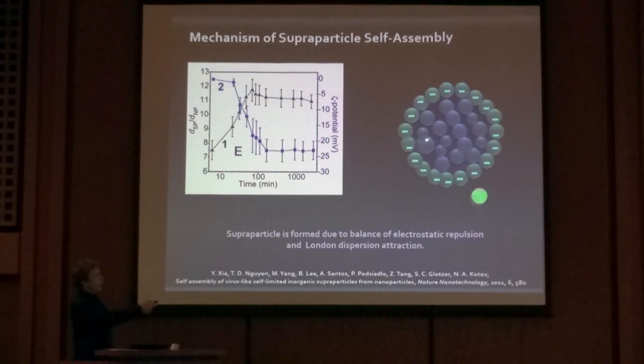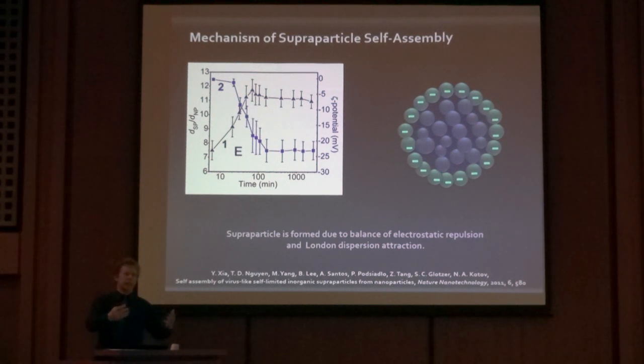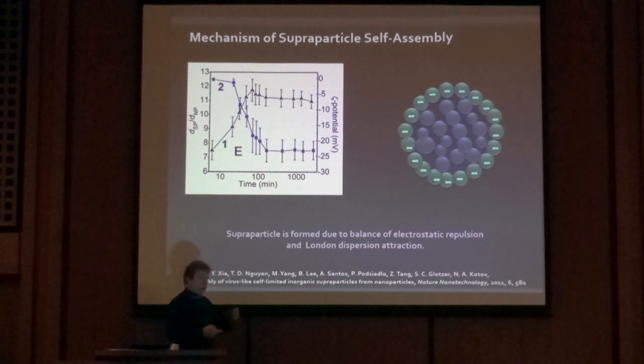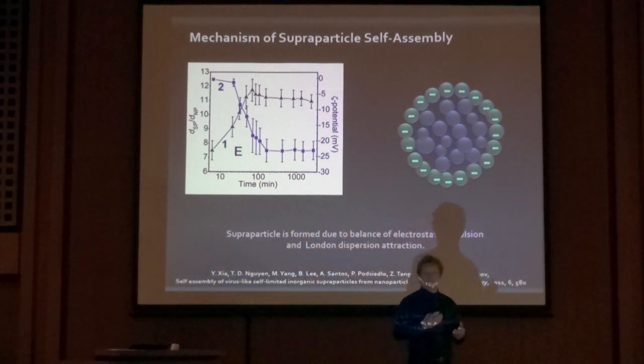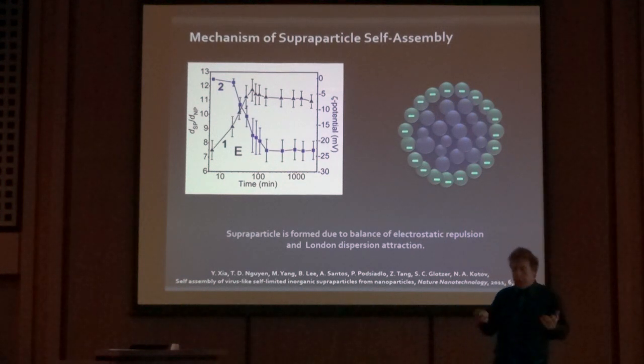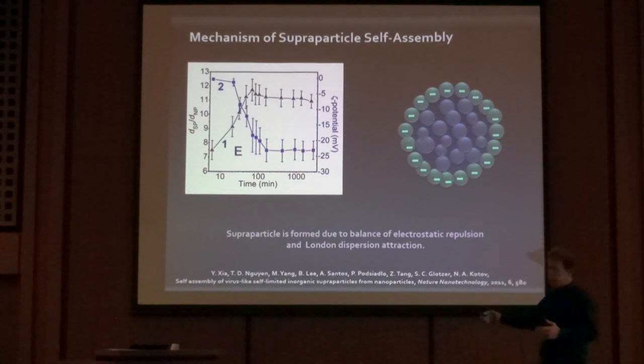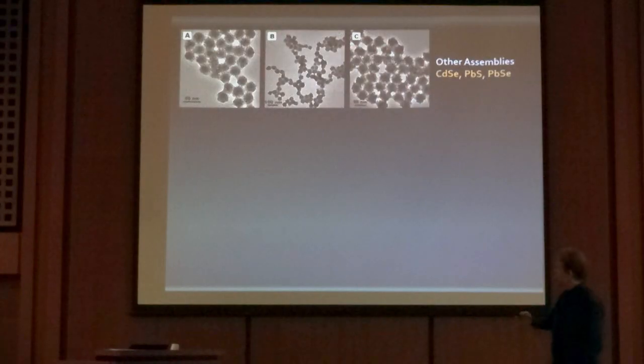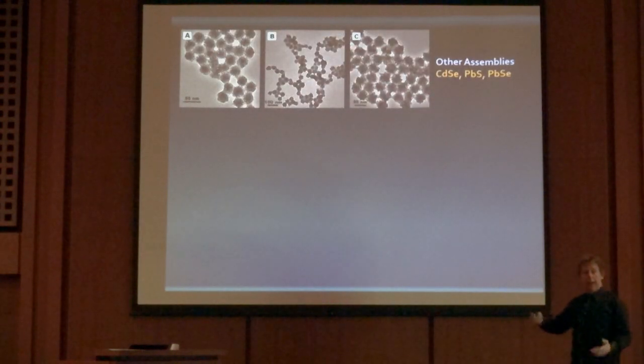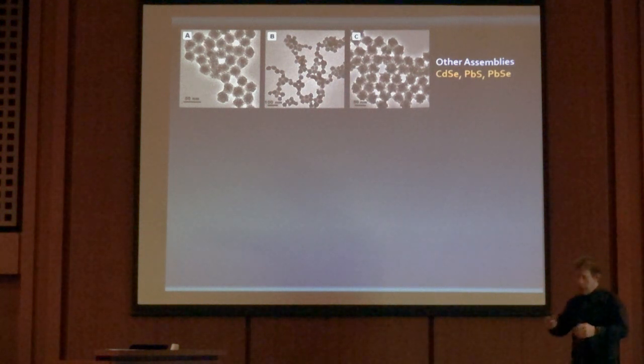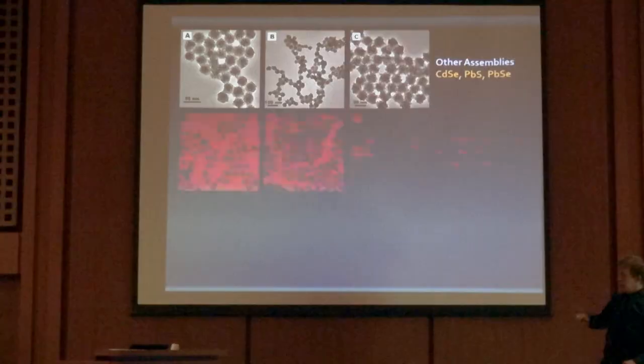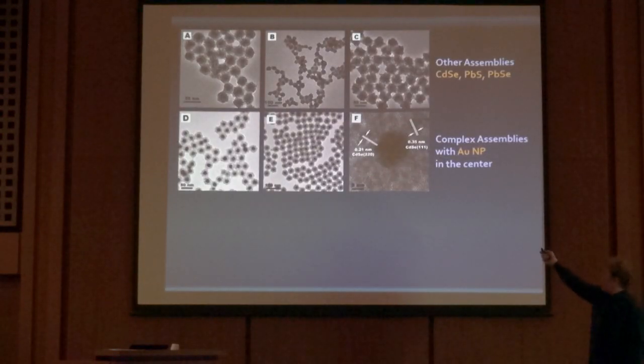So eventually, when we have the particle that would love to join the growing superparticle, it cannot, because the van der Waals attraction is not enough anymore due to the electrostatic repulsion. And that means that we can replicate this kind of terminal assemblies for many particles. There is nothing special about cadmium sulfide stabilized by citrate or shape of the particles there. We can carry out the same kind of assemblies as long as the particles have the same size, the same charge, for many other semiconductor particles or the combination with the metal particles.